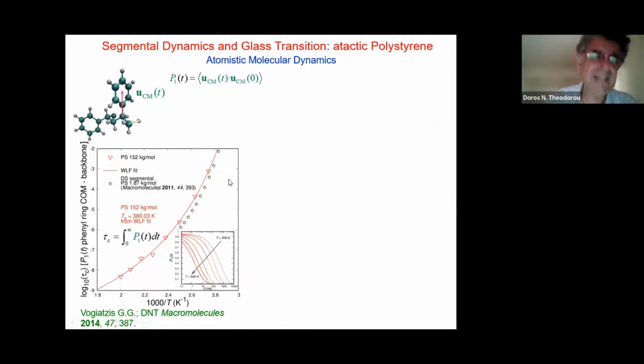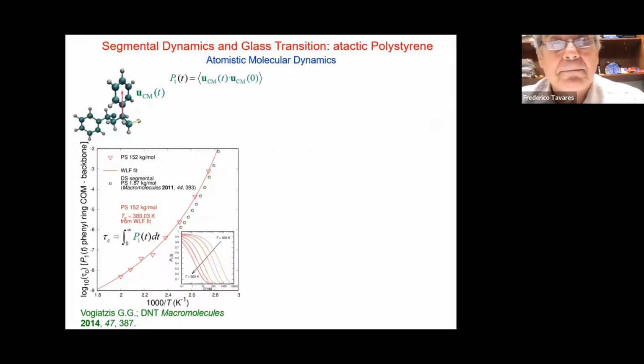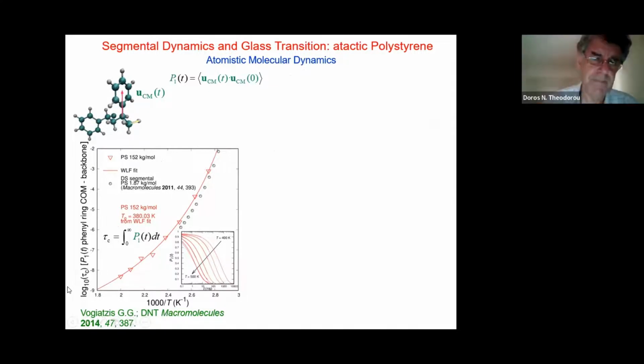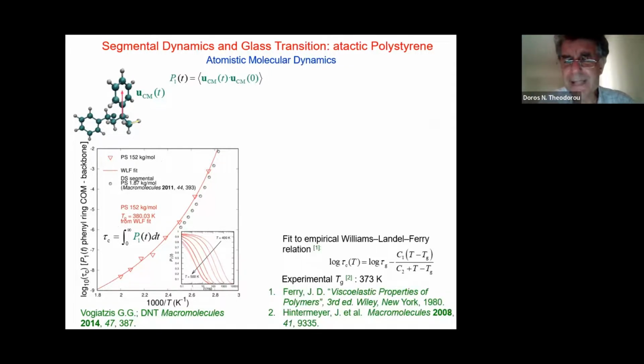And then you can integrate this P1 of t and calculate tau c. That's the correlation time for segmental motion. Now, we plot this as a function of inverse temperature, and there are several things one can do here. What we typically do is we fit that to a WLF or a Vogel-Fulcher-Tammann, which is exactly the same thing. It's mathematically equivalent. And from that expression, we calculate as a parameter this Tg.